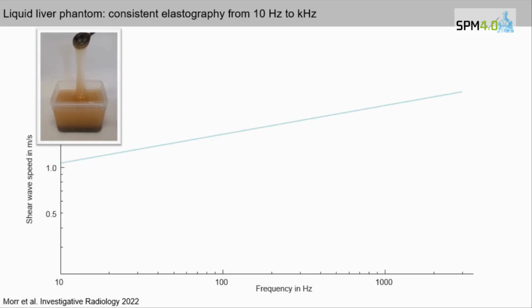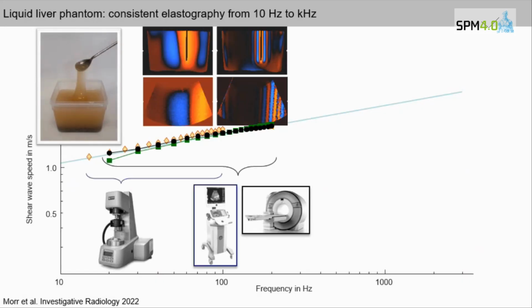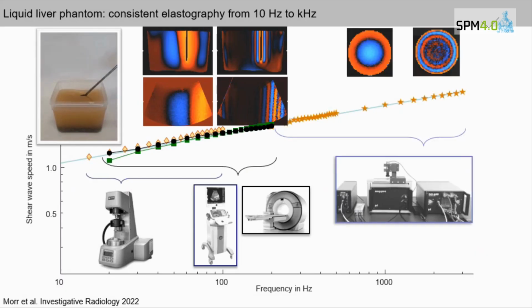In this frequency range, the behavior is quite well reproduced by our liver data. So this is just measured by different modalities here, reproducing the increase of shear wave speed over frequencies in different modalities from shear rheometry to tabletop MRI. But interestingly, the Springpot model is good in our frequency range, but cannot predict static deformation of the liver, right? Because it's a power law which approaches zero shear modulus at static conditions with zero frequency. It's undefined in this range.